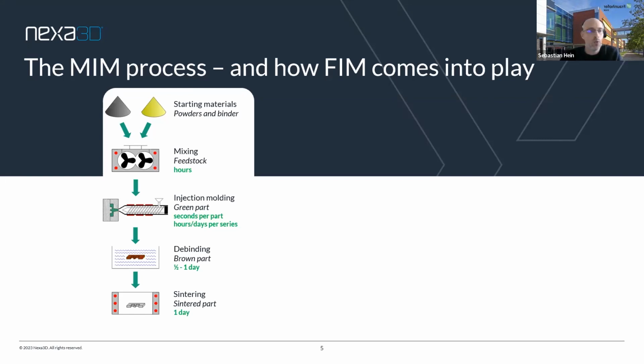And then, of course, this tool is usually opened up and the parts, the green part as we call it, are ejected, which is still a powder and binder mixture. Then we have to remove this binder, which is usually a two-step process. It can be done as shown here, either by dissolving some parts of the binder system, or by a chemical reaction, which is used, for example, for the Catamold feedstock that we show later, where a chemical reaction decomposes a part of the binder system, just not all of it, just enough to get